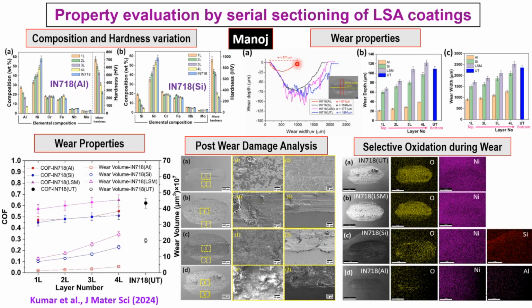And then if you look at the results, you see with the surface alloyed sample you actually have very high wear resistance compared to the as-received 718. These are the various wear damages at various depths, coefficient of friction, and how the wear looks - this was essentially fretting wear analysis.